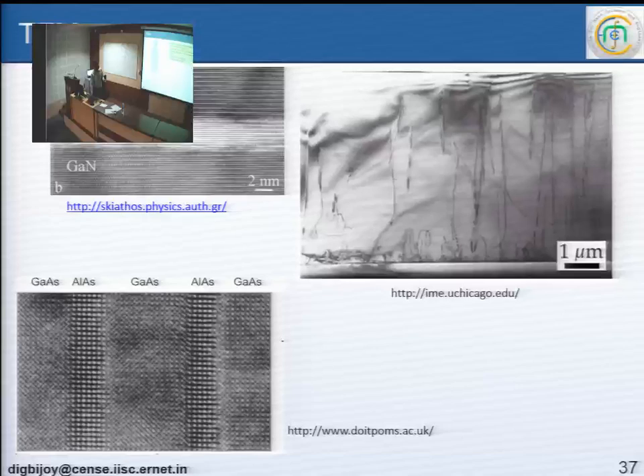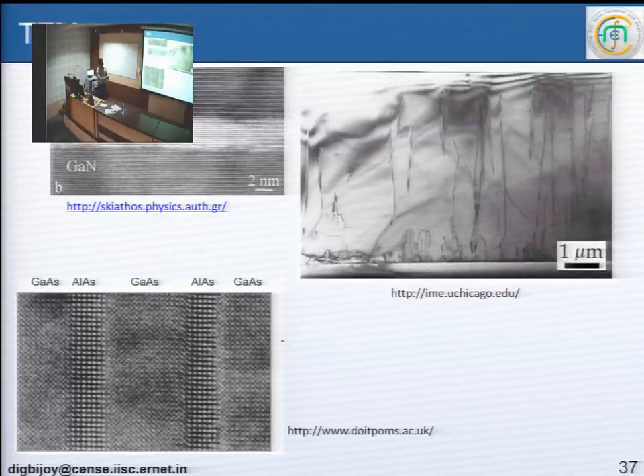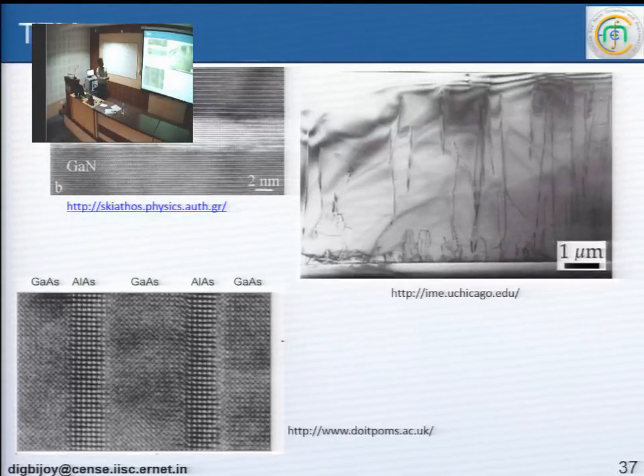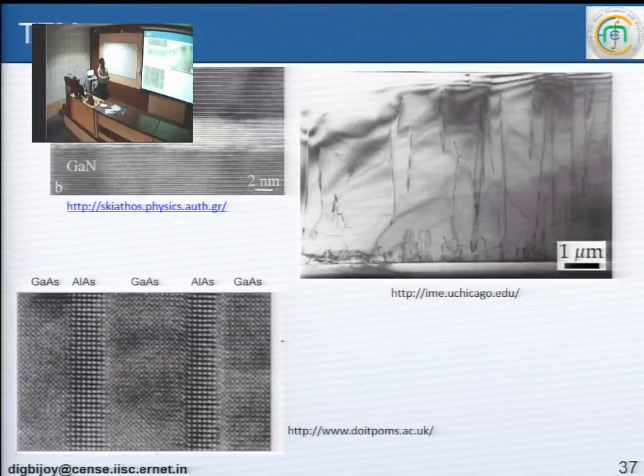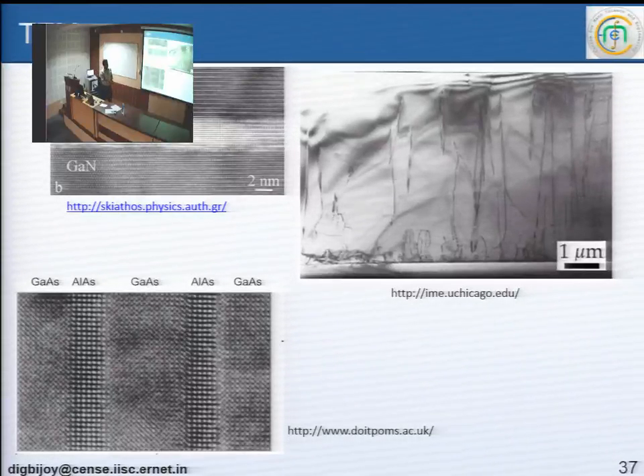So for example, this is a cross-sectional view of gallium nitride, aluminum nitride, gallium nitride. See, these are almost atomic layers that you see in cross-section, right? So this is one type of mode, and you see this is 2 nanometers. This height is probably like 3-4 nanometers, right? This is a dislocation. So you see, this is the substrate on which you are growing gallium nitride. Dislocations are a missing line of atoms, I told you, right?